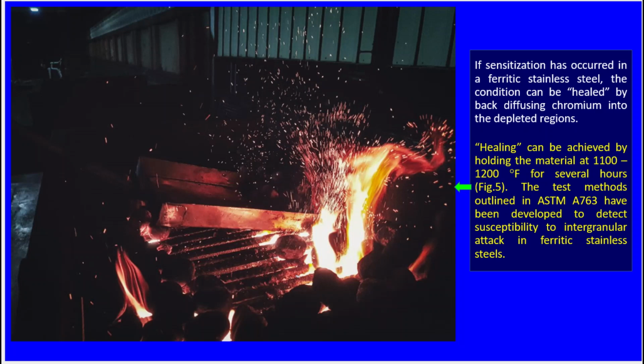The figure schematically shows how to achieve healing of the stainless steel over several hours. The test methods outlined in ASTM A763 have been developed to detect susceptibility to intergranular attack in ferritic stainless steels.